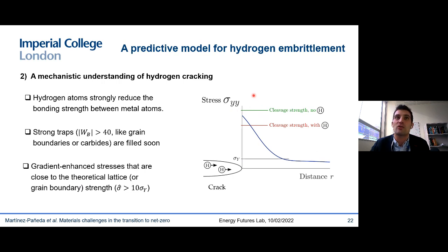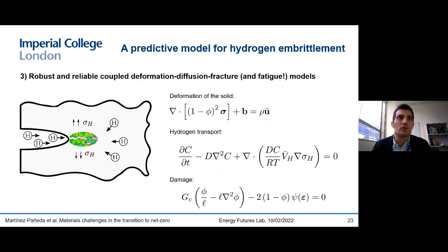However, the moment you bring hydrogen into the picture, then you lower the cleavage strength, these two lines cross, and automatically you have a model that is able to capture how you go from this ductile fracture process to a brittle fracture process with no fitting parameters whatsoever. You just tell it now hydrogen comes into the picture, and the model automatically is able to capture the shift from ductile to brittle. So that is great news, and that takes me to the last third front that we